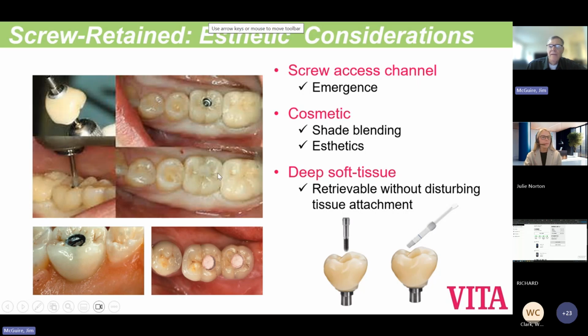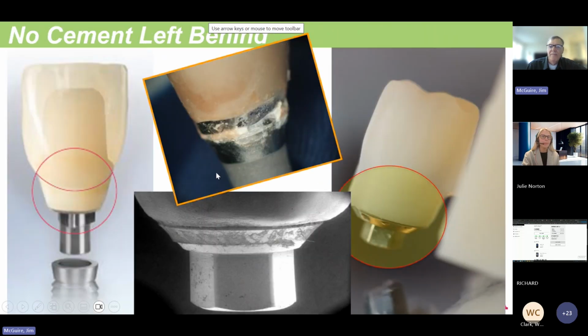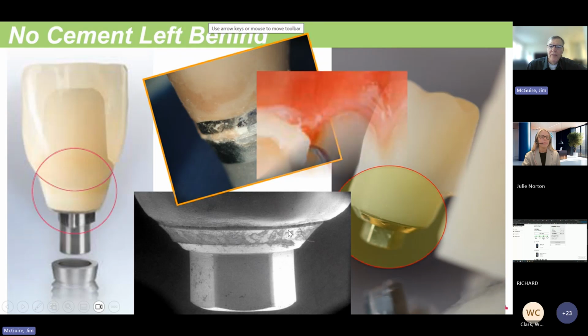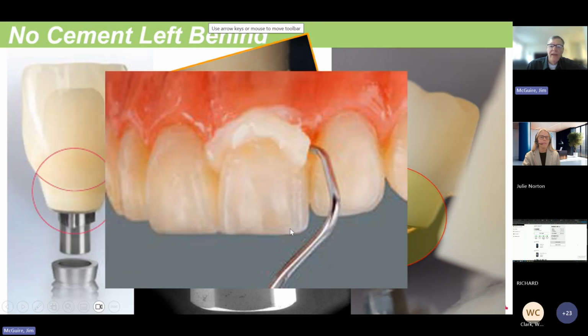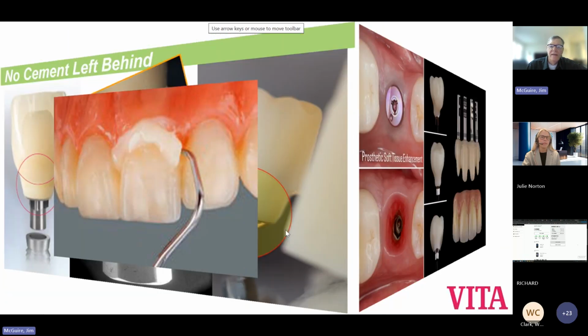and then you can use a composite and light cure that together to make it more cosmetic. Again, if you don't get rid of your cement overflow, you're setting up to have a potential failure of that implant because of inflammation. So make sure your crowns fit well to your titanium abutment, especially the collar, and make sure you're able to go back and clean everything off as needed.